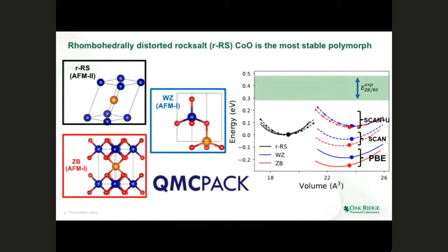So for this end, what we did was to first understand whether the code and the pseudopotentials that we use are accurate enough to simulate the cobalt monoxide itself. So basically, we know that there are 3 different polymorphs of cobalt monoxide, which are rhombohedrally distorted rock salt, wurtzite, and zinc blende structures. So when we simulated these 3 polymorphs using PBE, SCAN, and SCAN plus U, we know from the experiments that the rock salt phase should be the most stable. And we are seeing that kind of qualitative behavior only when we try to use the SCAN plus U calculations in here.